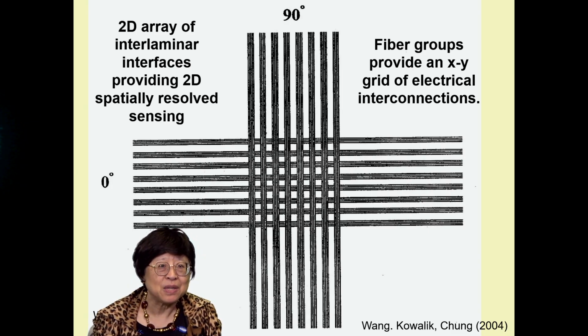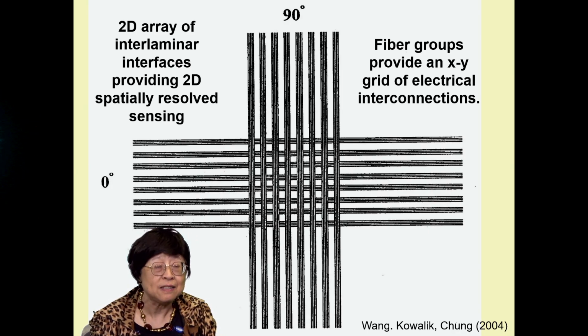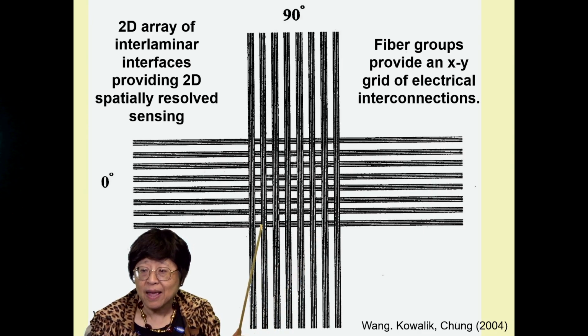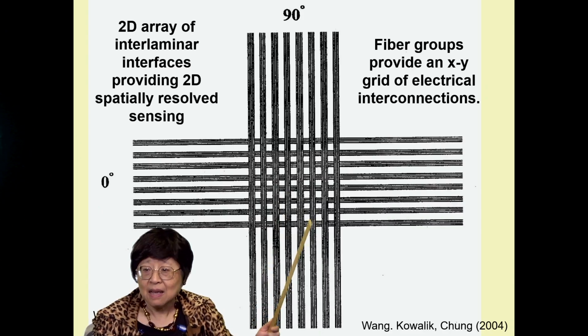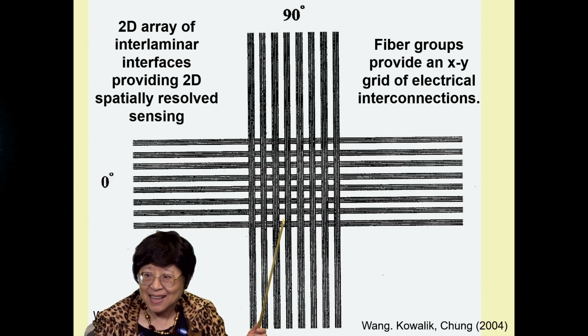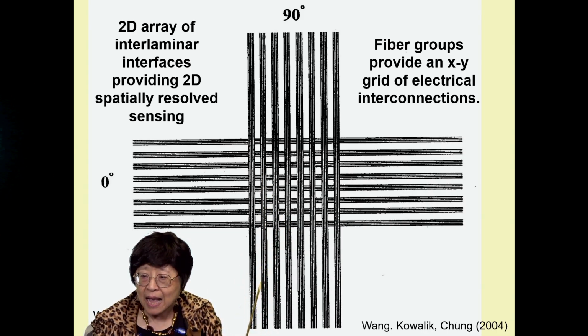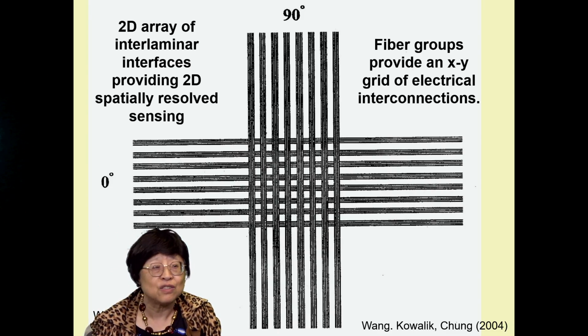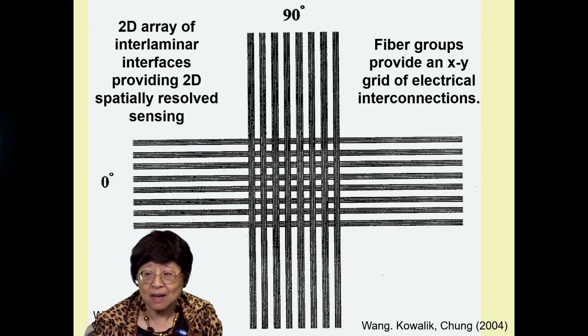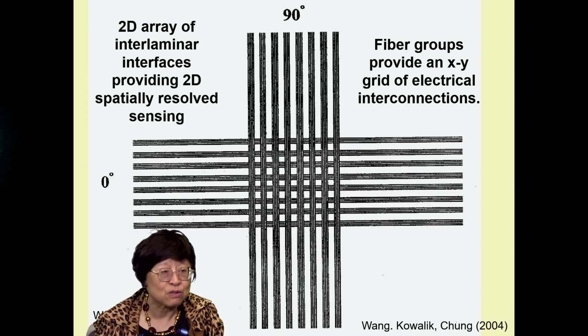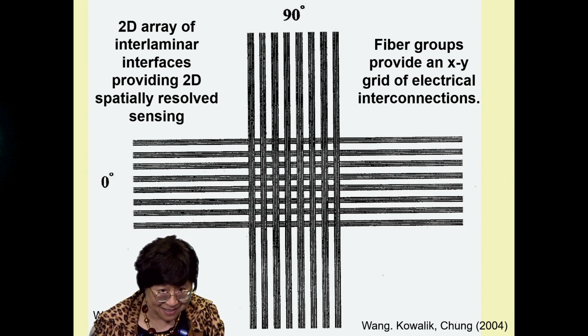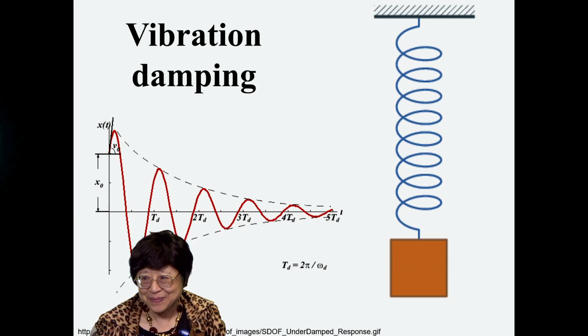Another nice thing about using the carbon fiber composites to sense itself without device incorporation is that you have a 2D array of these interfaces, see? And so you have a 2D array of sensors, thus allowing spatially resolved sensing. In addition, you have this XY grid of electrical interconnections provided by these fiber groups. So you have sensors as well as electrical interconnections all built into the structural composite.